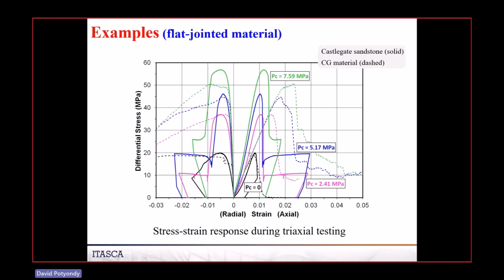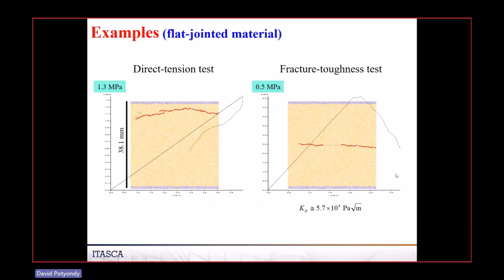Then we go to the pink curve. That's 2.4 MPa confinement, and notice that it's stiffer and stronger. And then we go to the 5 MPa curve. You can see that as you increase the confinement for this material, you're increasing its strength and its stiffness. The dotted lines are the PFC material subjected to the same confinement conditions. And what we're seeing here is the PFC material has the same slope because we don't have any initial cracks in this system. It's all well connected for this model. But notice how the strengths, we're getting about the same strength increases with confinement as we were for the Castlegate sandstone.